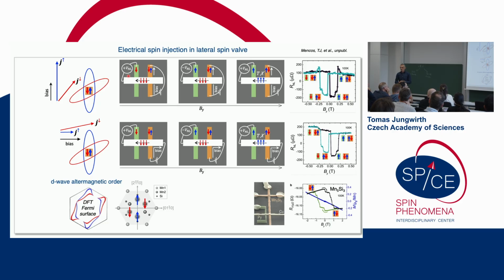Oh, that's because you have a shape anisotropy. Yeah, so it's an in-plane permalloy, so it will be weakly anisotropic, but because of the shape anisotropy, you make it along. But then the anomalous Hall would be RXZ in this. Now the anomalous Hall, that's interesting. This is an altermagnet, this is not the permalloy. This is the anomalous Hall effect in the altermagnet. You can apply the magnetic field either out of plane or in plane, and you can still switch the Néel order, and you see the anomalous Hall effect. Okay, so this is really a Y magnetic field, along the y-axis. It's very different from a ferromagnet, what you're usually used to.